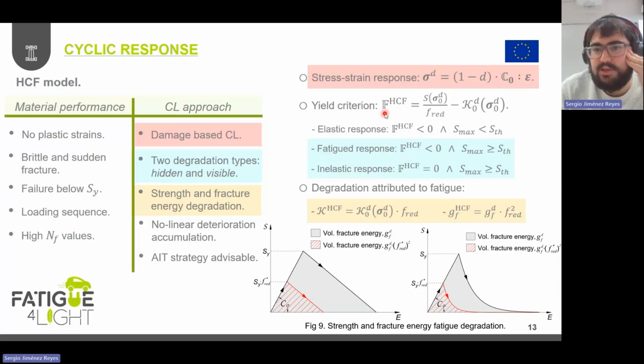And basically what I'm doing, this is exactly the same yield criterion that I presented for the damage case, but now I'm introducing this term, which is the term that governs the fatigue response in our constitutive law. And I will describe it later. Just for you to know, this fatigue reduction factor term ranges from 1 to 0, 1 for virgin conditions, and well, it's not necessary to be 0, but a minimum level. I have some examples there where the minimum is set to 0.1.